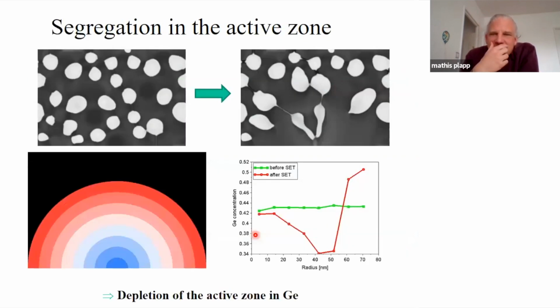And here is a somewhat more quantitative analysis where we have averaged the composition field over these annuli that are colored in different colors here. And we can compare our composition from before in green and after the operation. And we can see that indeed some of the germanium has been expelled from the active region, which is here, toward the external regions, which is here. We have sort of a wall of germanium here outside of the active region and the depletion inside.